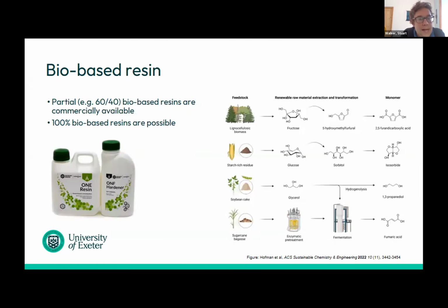We can also have a bio-based resin, either with the bio-based fiber or in a glass fiber usage. So similar to how we can make bio-based polymers, so plastics, so we can make PET and HDPE, for example, from bio-based sources through breaking down things like sugarcane and forest residues and things like that. We can break them down into the chemical building blocks that we use to make these polymer products. So we can go through that process, and we can get 100% bio-based resin. It's currently much more economically viable to have a mixed resin, so a partially bio-based resin and partially fossil-based, but the 100% bio-based resin is in theory possible.